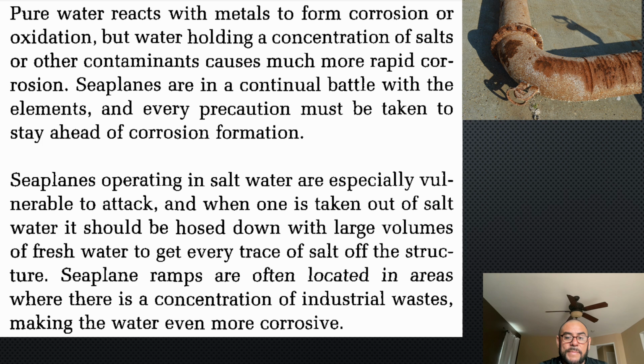Now, pure water reacts with metals to form corrosion or oxidation, but water holding a concentration of salts or other contaminants causes much more rapid corrosion. Seaplanes are in continual battle with the elements, and every precaution must be taken to stay ahead of the corrosion formation. Some of you might end up in Alaska, right? In Alaska, there are a lot of seaplanes operating in salt waters, and those are especially vulnerable to attacks. When one is taken out of the salt water, it should be hosed down with large volumes of fresh water to get every trace of salt off the structure. Seaplane ramps are often located in areas where there is a concentration of industrial waste, making the water even more corrosive.